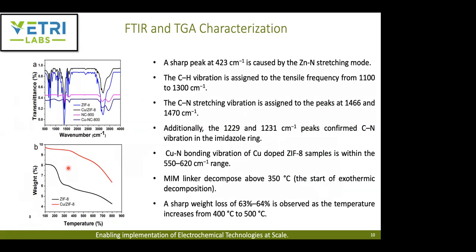So with the FTIR, you can see a sharp peak at 423 wave number, which is caused by this zinc-nitrogen stretching mode, suggesting that the linker zinc and the nitrogen atom are bound to form this porous ZIF coordination structure. And you can eventually see this peak is not present in the pyrolyzed copper-doped nitrogen-doped carbon at 800, confirming that zinc is completely removed and there is no zinc-nitrogen bond.